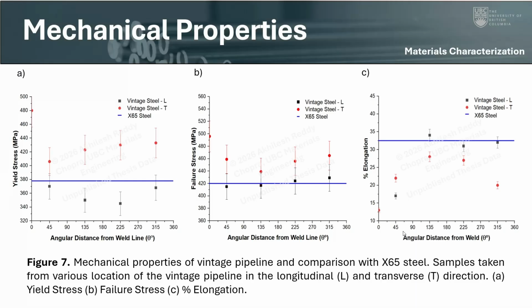Under loading along the longitudinal direction parallel to the weld, we can expect or hypothesize that deformation proceeds along the inclusion orientation. So as I mentioned, if those inclusions were elongated and rolled in that same direction, then we would expect to see higher ductility versus transverse to the direction. If we apply a load perpendicular to the elongated inclusions, then we observed a lower fracture stress and also a lower percentage elongation, which corresponds to the ductility or the brittleness